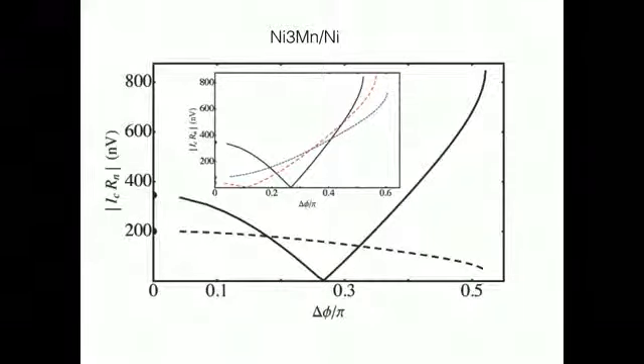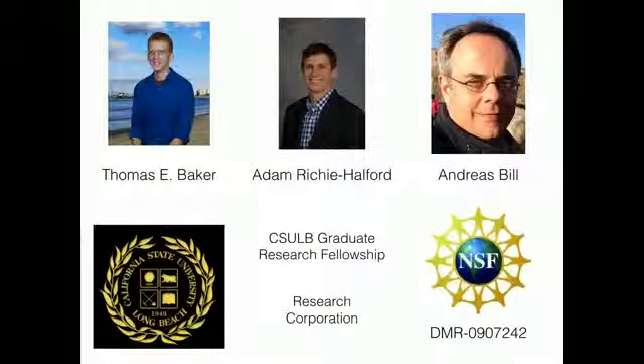The long-ranged triplet components always drive the current in one direction that we call negative by convention. The singlet contribution to the current from the superconductor is also present, due to the weakness of the ferromagnet and modified by the cascade effect. The thickness of the layer is chosen so that the singlet contribution to the current is in the positive direction in this sample.